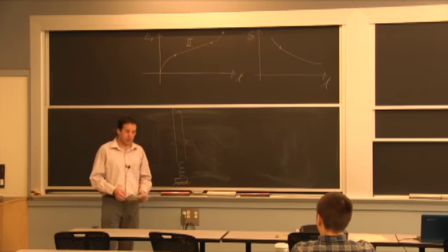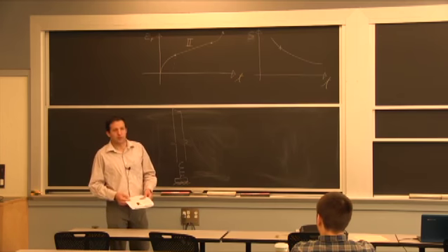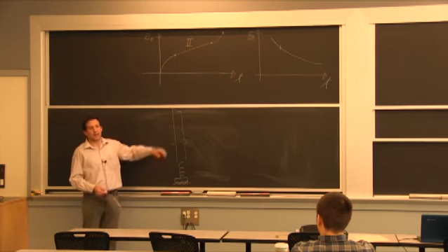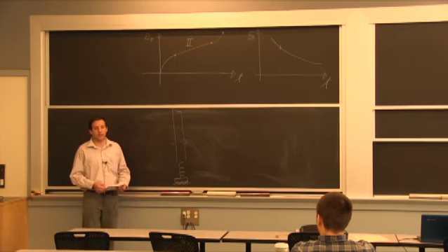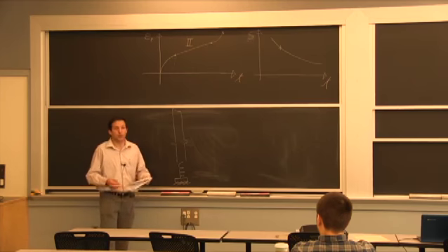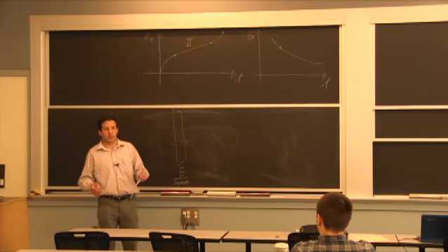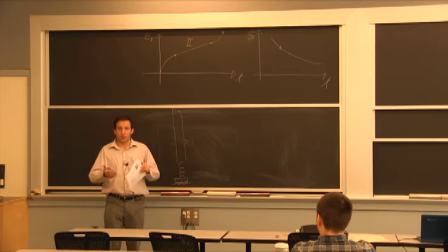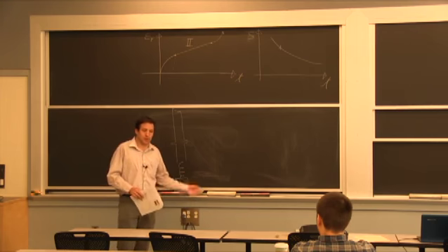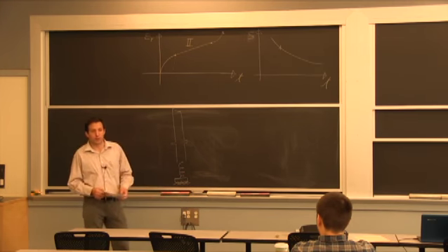It doesn't take away from the dislocation aspect, because even if this is a single crystal, it does have a bunch of dislocations in it, and when you deform it plastically, it will not behave in as good a way as a polycrystal. So the deformation is going to tend to localize in specific planes. So you try to avoid that. You still try to essentially avoid creep on those components to the extent you can.